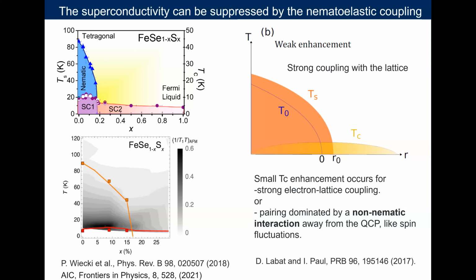First of all, indeed, those fluctuations are suppressed by this strong electron-lattice coupling. But another reason could be that those fluctuations are not responsible for superconductivity. And if spin fluctuations are only found inside the nematic phase, they are dying away as we go outside.